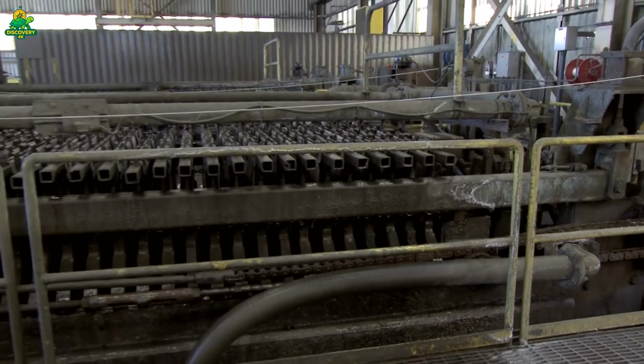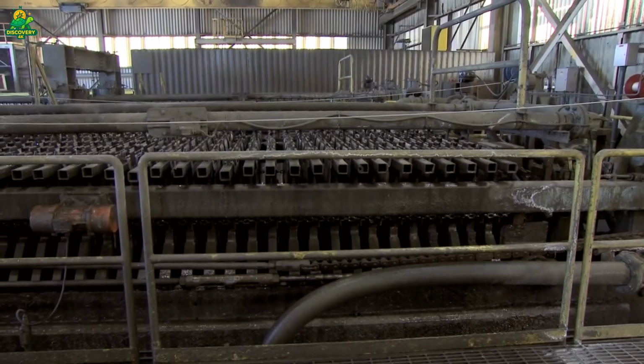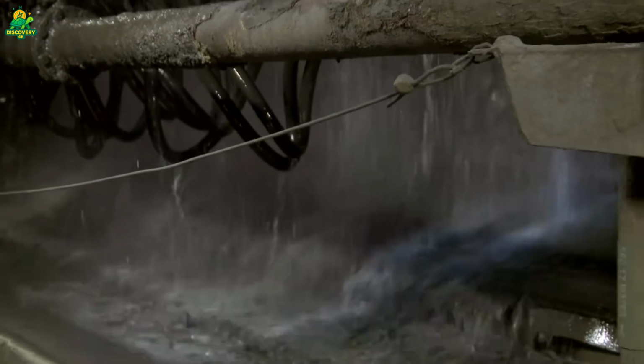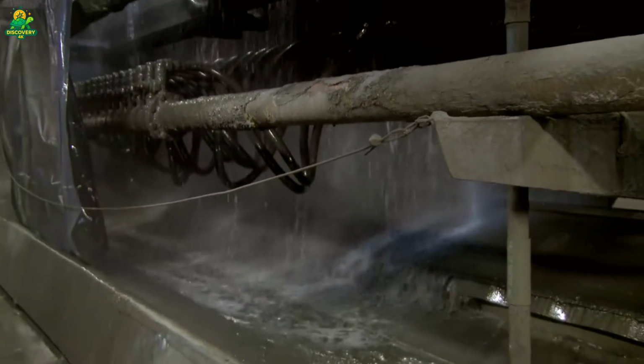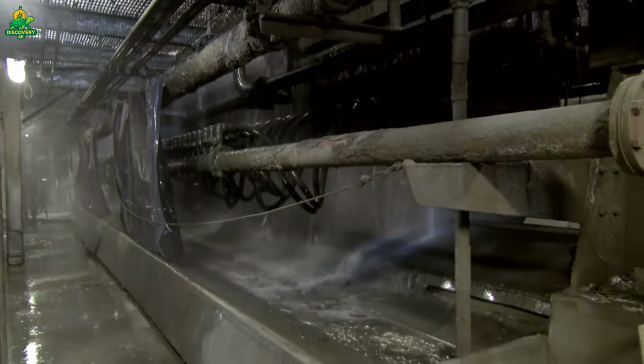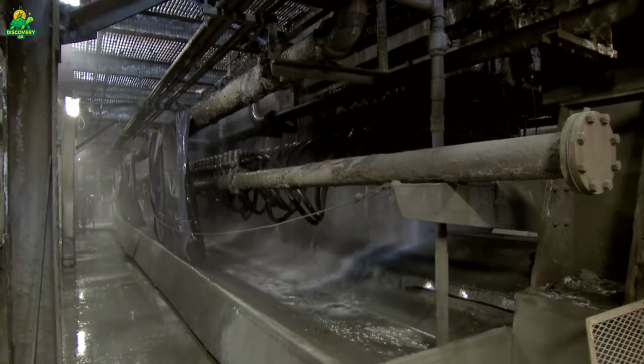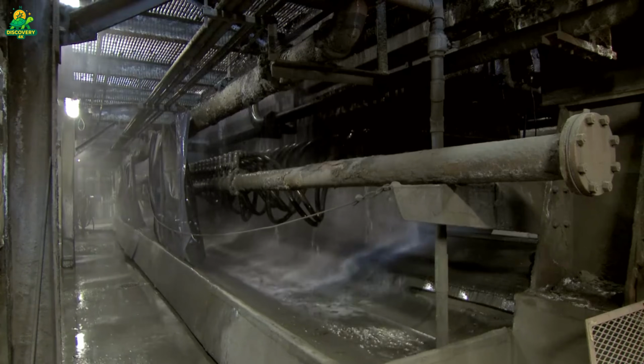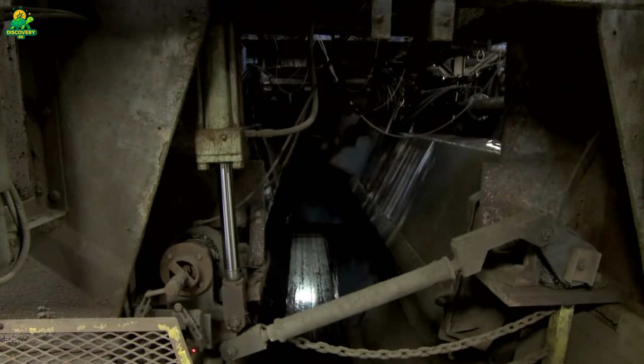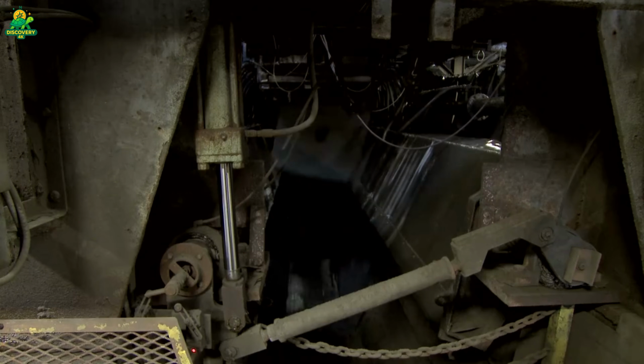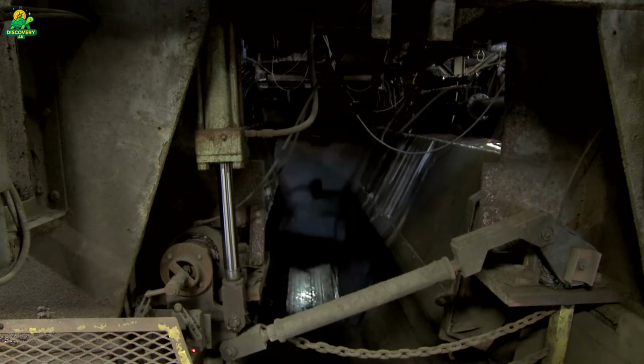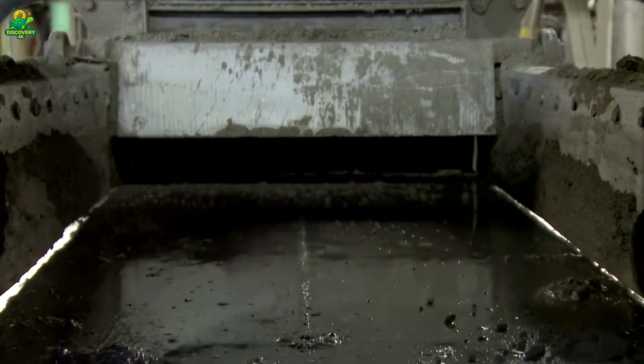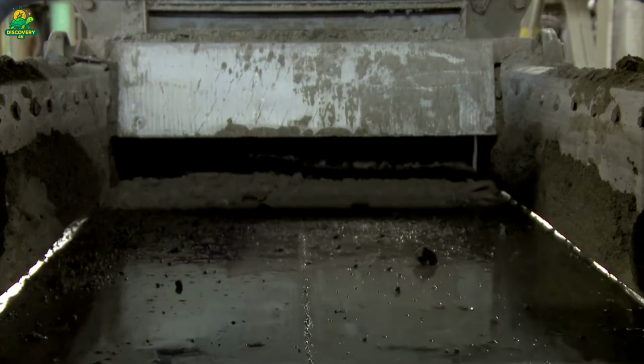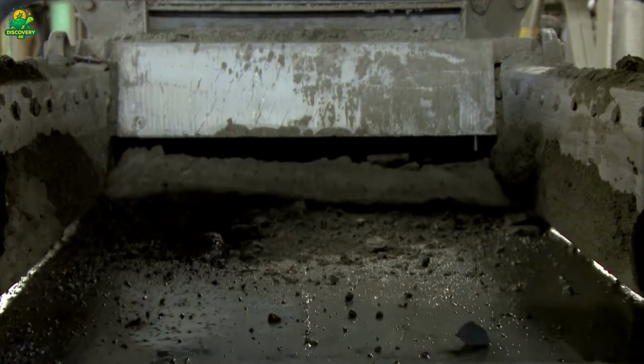Now the material is ready for one of the most dramatic transformations in metallurgy: smelting. The concentrate is dried and fed into massive furnaces operating at temperatures above 1,200 degrees Celsius. At these extreme temperatures, the material melts, separating into layers. Impurities form a molten slag that floats on top and is removed, while the copper-rich material settles below. The result is a product known as blister copper, typically around 98 to 99% pure.